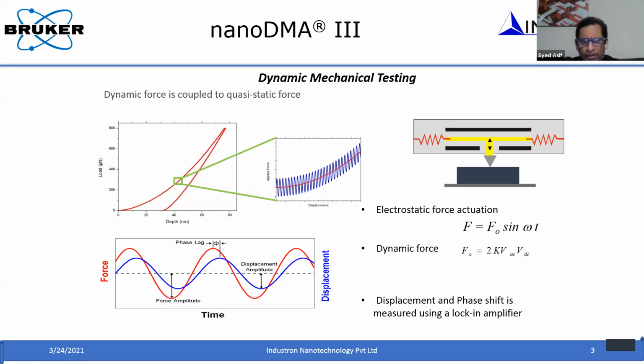To avoid that, we introduced a simple technique, which is a force modulation technique, or in other words a dynamic mechanical analysis at nanoscale, where we superimpose a small sinusoidal force on top of this quasi-static force and measure the displacement response to the force that you apply. This is quite similar to how radio broadcast works, where you transmit at a frequency from the station, and at the receiving end you tune to that frequency and listen to the radio, right? It's the same way. You oscillate this force at a known frequency, and then you have the electronics to listen only at that particular frequency to how the transducer responds, how the material responds.